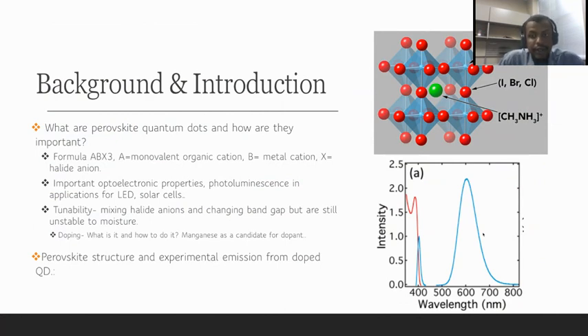So they also offer a high degree of tunability by mixing the halide anions, and that will change the band gap as well. But they're still unstable to moisture, and this instability is maybe caused, I think, by the dynamics of the ligands and the atoms that they're attached to, because it's ionic bonding, I guess, between the ligands and the atoms.